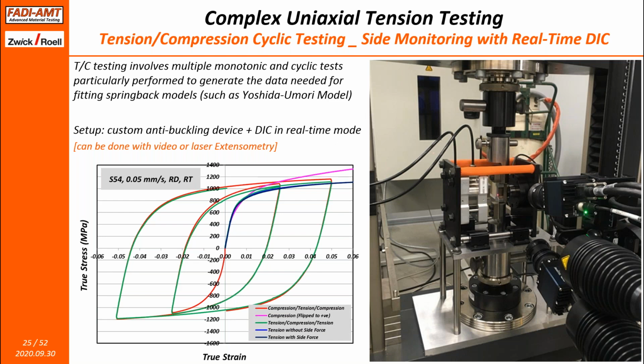And then we need to monitor or measure those strains. The difficulty here is with an anti-buckling device, as you can see in my picture on the right-hand side, the sample is technically buried. You can't see it because now we can only see the thickness, or through the side of the material or the sample. And if the material is like 1 or 2 millimeters thick, that is almost all you have to monitor the material and measure the strains. And those strains are extremely important to measure.